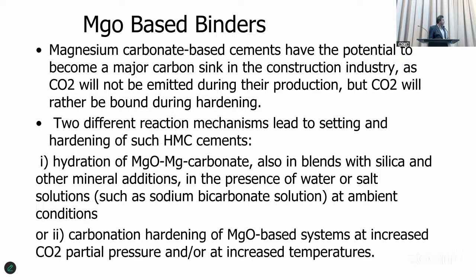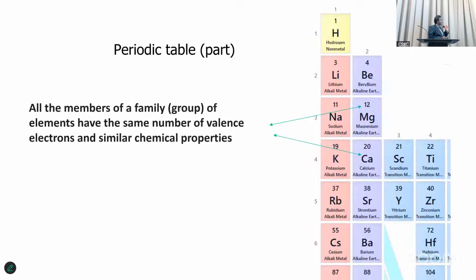And the second one is the carbonation hardening of magnesium oxide based systems at increased carbon dioxide partial pressure and at increased temperature. That will harden these magnesium oxide based systems as well. So the carbon dioxide captured from cement production can really be used for these binders. And again, as I said, this will be more. So, back to basics.